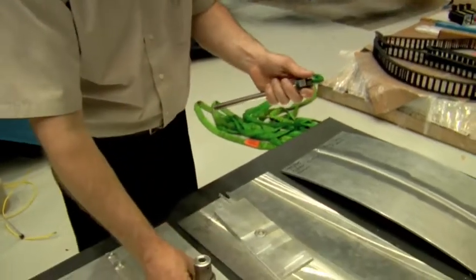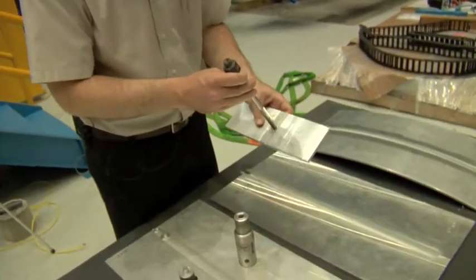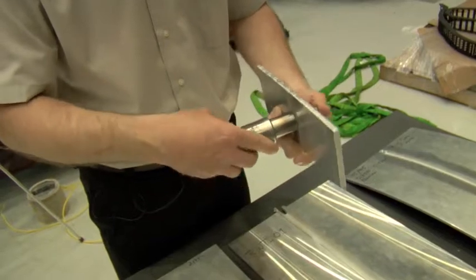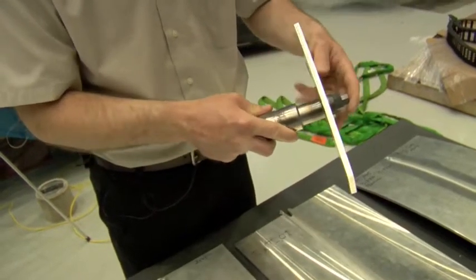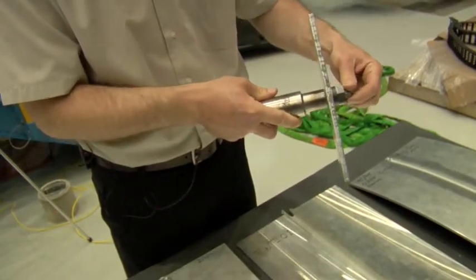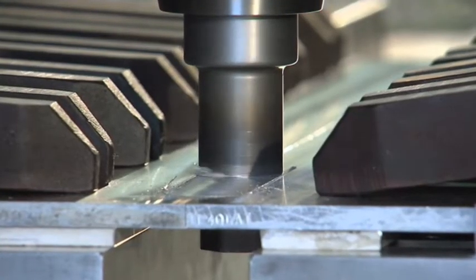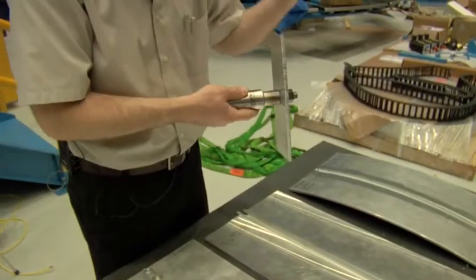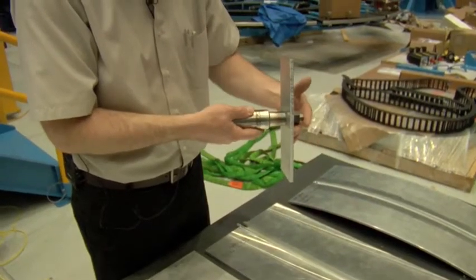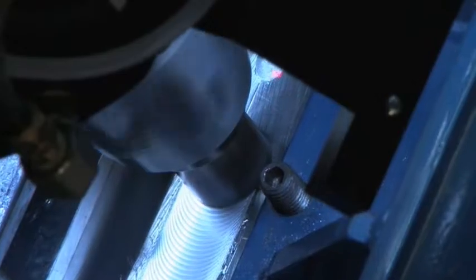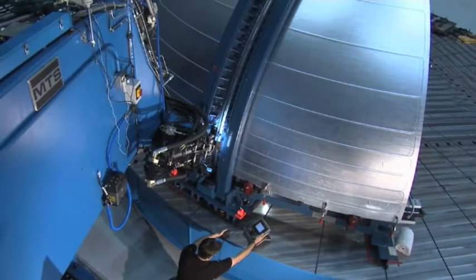And what we do in self-reacting is rather than having this type of pin tool which we push against a solid backing anvil, we actually install the tool in a plate like so, and we pinch the part between two shoulders while this assembly is rotating and traveling. So in this process what we do is we've eliminated the need for a backing anvil. The benefit there is it makes our tooling somewhat simpler and easier to fabricate when we're building large scale.